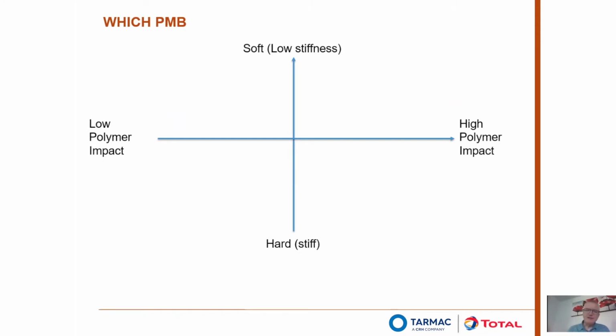So if we think about the behavior of the polymer modified bitumens in terms of these criteria, the Styrelf range that we manufacture at Total, we can put on this chart where the different grades are. So our Styrelf X70, which is effectively our basic grade of polymer modified bitumens, is going to lie at the lower polymer impact. So these are a slight improvement on penetration grade materials. Being a 70 pen, it's sort of average penetration.